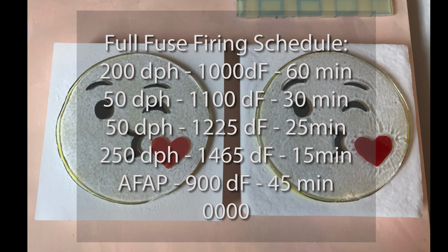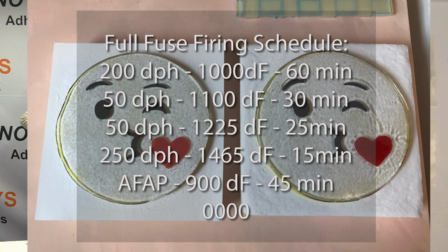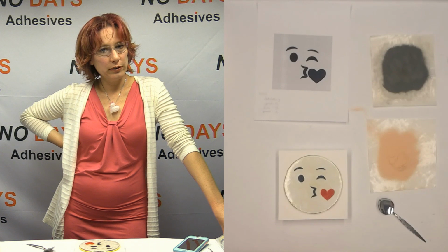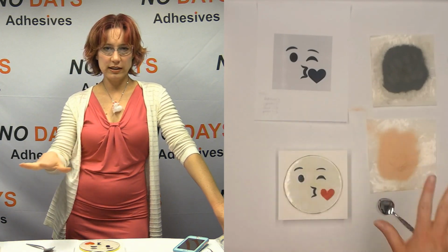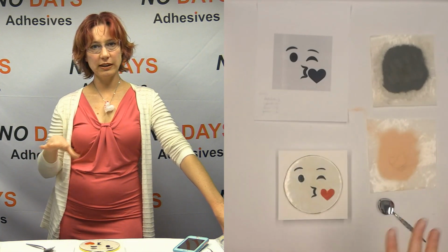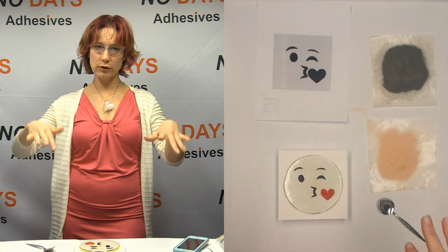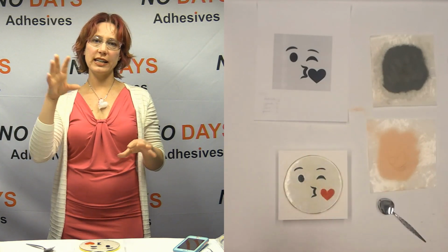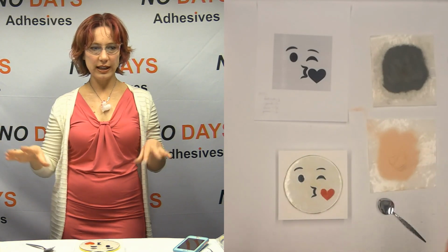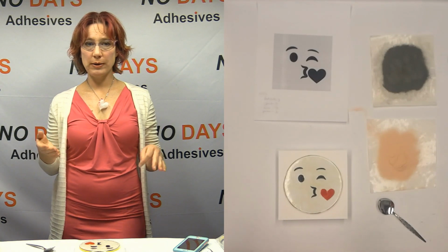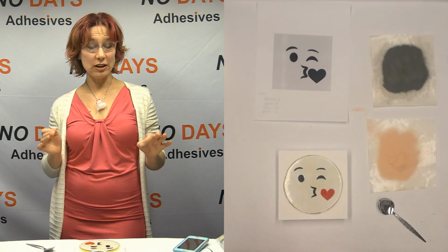I don't have any binders that I'm burning off now at this point, so I don't have to worry about going super slow. But I've got a bigger kiln, and I'll probably be firing a bunch of this in my bigger kiln. Whenever I'm firing on a ceramic shelf, these are going to go all across the ceramic shelf. I'm going to space them out as evenly as possible so that the heat hits the ceramic shelf. It doesn't have areas that get a lot of heat and areas that don't get a lot of heat. That can be an issue for your ceramic shelf. It can shock. It can actually break.